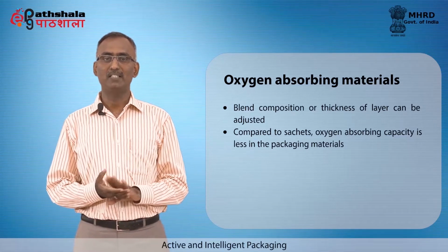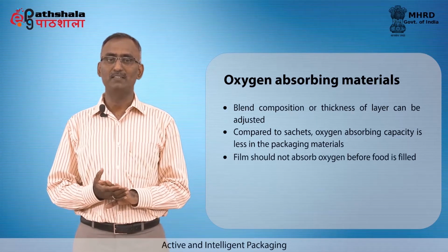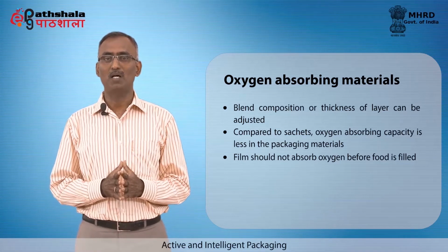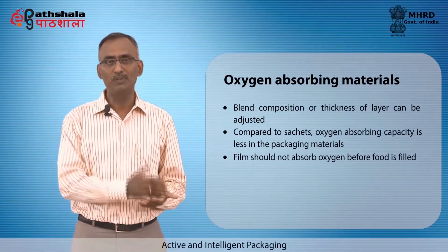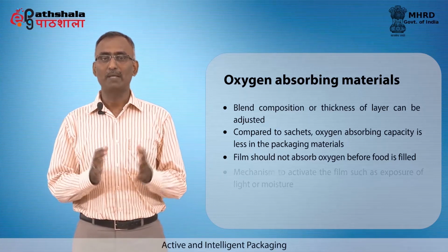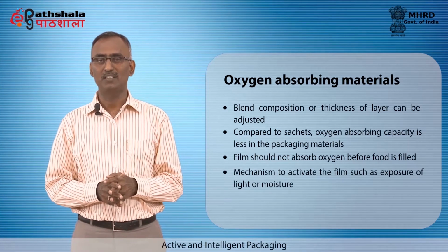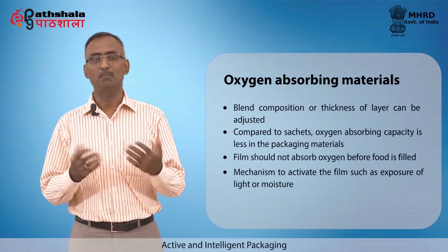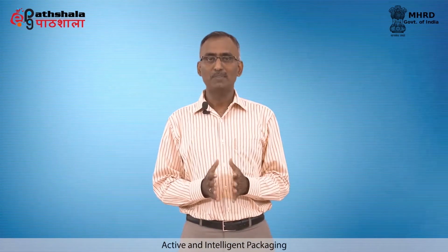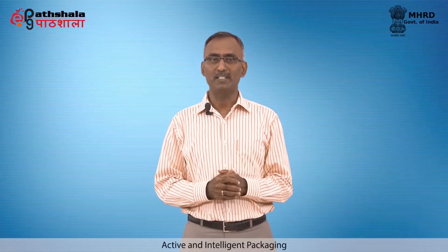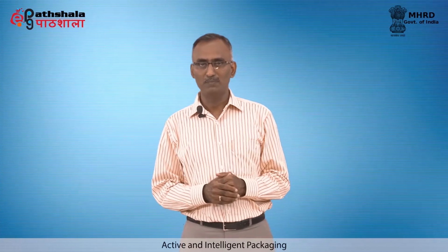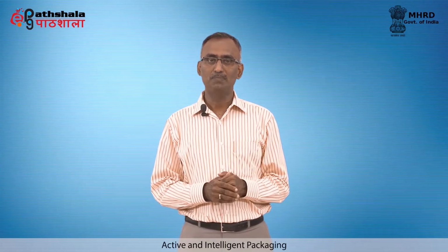The major challenge in manufacturing this type of film is that the film should not absorb oxygen before food is filled into it. There should be some mechanism to activate the film, such as exposure to light or moisture. In some cases, when the polymer based absorber is co-extruded with packaging materials like bottles, films, can coatings, these packs absorb oxygen in the headspace and prevent the entry of oxygen into the packs.